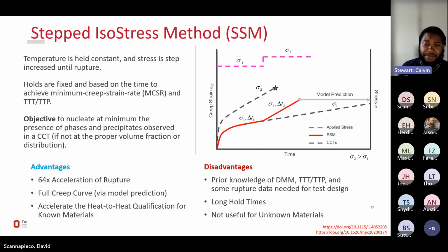So we're going to go into rapid, and I'll discuss some of the work that my team has already done, and we're going to focus in on creep because that's an area of interest in my group. One of the non-standard tests that we've developed is called the stepped isostress method. In a conventional creep test, you hold stress constant, or a constant load, constant temperature, and you wait. You wait until it fails. It could fail in a month, it could fail in a year, it could fail in 10 years, depending on the combination of stress and temperature. And when that specimen fails, you have one data point, one curve that gives you information about how that material performs, and that's only at that stress and temperature.